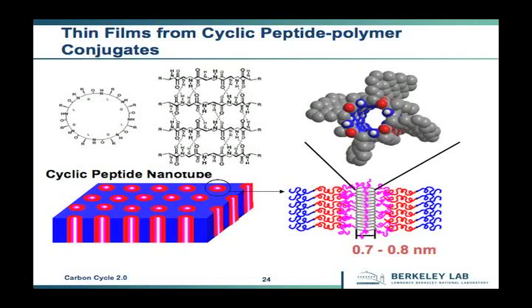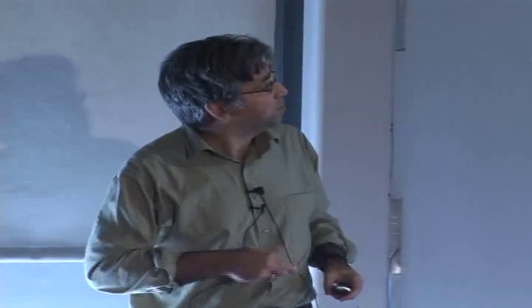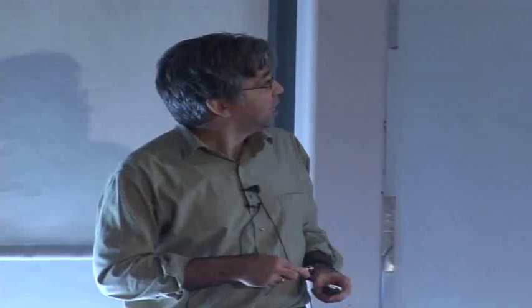Another interesting material is based on cyclic peptides, which are made here in the Foundry. So what they can do is make cylindrical peptides, which you can actually see here. They form a hole where you can tune the interactions again by introducing additional chemistry. And what Brett Helms and Ting Su have done is they have attached polymer arms to those cyclic peptides, which you can see as the gray ones here. And if you put them together, and only Ting can do this in the world, I think, if she puts those things together, they spontaneously form such a membrane.